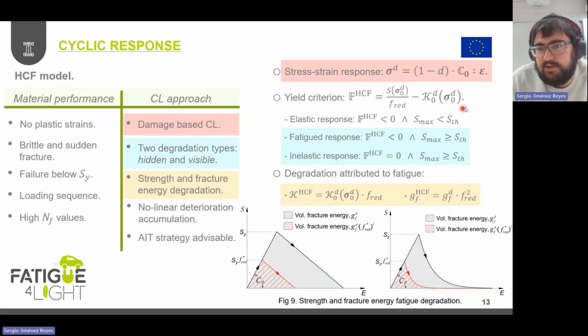That progressively degrades or diminishes the strength of the material, or here in this yield criterion, what I'm doing is amplifying the stress state of the material. Both are equivalent. And then in order to achieve failure below the yield strength, what we need to do is somehow reduce the strength of the material and the fracture energy along this fatigue response of the constitutive law. And we do that by diminishing, as I was previously commenting, the strength through this fatigue reduction factor, but also reducing the amount of fracture energy available in the material, and they result in this type of response. Okay, I have some examples afterwards, which may be more visible and evident of what I'm doing here.